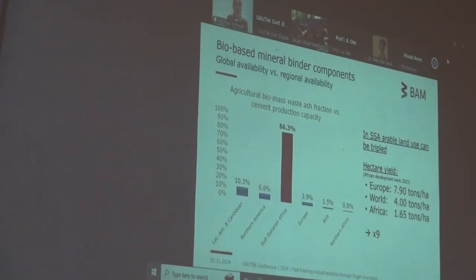The arable land use in Africa could be tripled. And for Africa, the average hectare yield is a third only of the world's average. So if the production would be only on the world's average and not higher, and all the arable land would be used, we could increase the amount of Portland cement production capacity up to 86.3% just by using the waste materials from food production. This is certainly a theoretic number, but if we only can activate 10% of it, we would already reach a lot. And these vegetable ashes can perform very well.